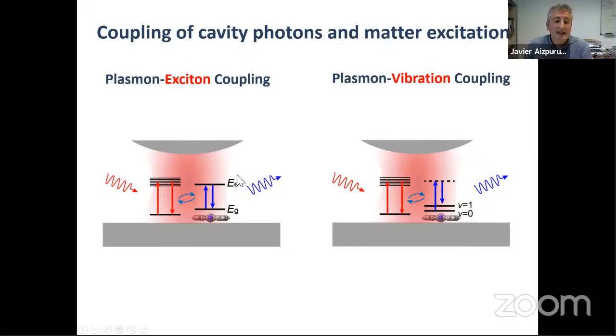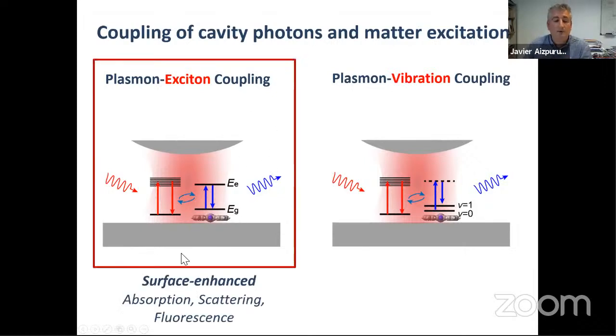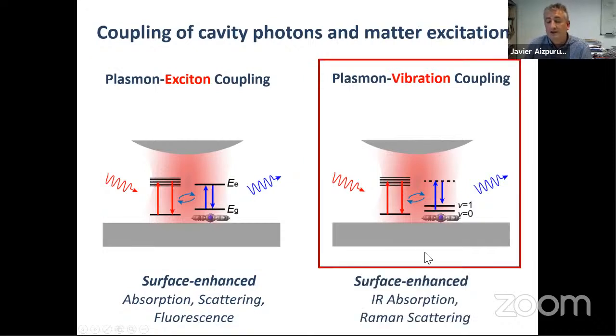So in this sense, when we use metals to improve these spectroscopies, people have talked about surface enhanced absorption or scattering or fluorescence. And when it comes to vibrations, people have also used surface enhanced infrared absorption, SEIRA, or surface enhanced Raman scattering, SERS. And the reason why people use this terminology comes from the 70s, when people just put the molecules on top of metallic electrodes in electrochemistry, and they saw that the Raman signal was improved by several thousand times. And they didn't know why this happened. And they called this effect a surface enhancing effect, like a surface enhanced spectroscopy.